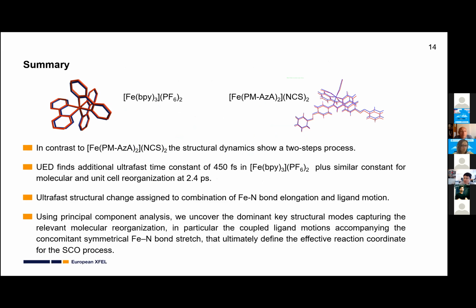So I'd like to summarize. In this iron spin crossover work, we show a two-step change. The fast one is 450 femtoseconds, the slow one is 2.4 picoseconds, and the fast one can be assigned to a combination of iron-nitrogen bond elongation and the ligand motion. Using the principal component analysis, we uncover four key structural dynamics modes to capture the molecular reorganization.